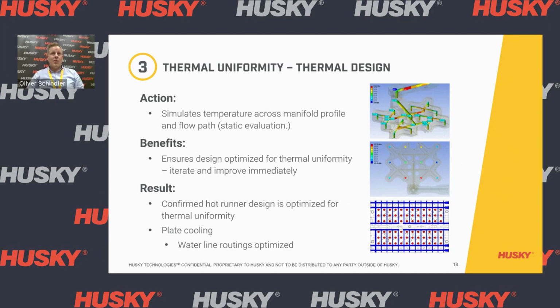So Husky performs a thermal FEA for almost each individual project. What does almost mean? Almost means that, for example, if you order a repeat system which already was performed with a thermal FEA, we would not start another FEA. So this simply means almost, but for each project, we do a thermal FEA prior to any manufacturing steps. And this means that we are adjusting the heater wrapping, the number of zones, the thermocouple placement, and melt channel layout with the heat sinks and all the manifold profile.